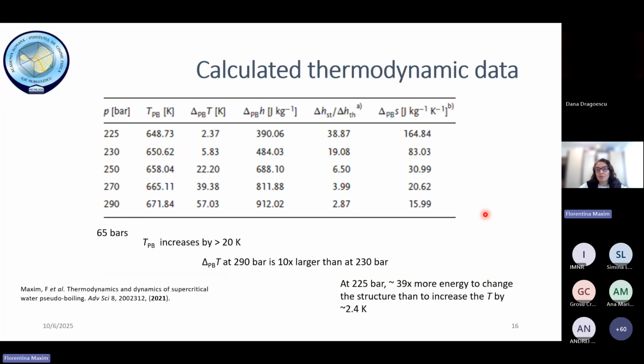Regarding the fundamental knowledge on pseudo-boiling transition in the supercritical water region, we calculated the thermodynamic data by pseudo-boiling theory, and we see that in the 65 bar pressure interval, the temperature of pseudo-boiling is increasing by 20 Kelvin. Also, the transitional temperature interval at higher pressure is larger than at lower pressures. But what is very important, at lower pressure we have a higher supercritical boiling number. That means that the system is consuming more energy at low pressure to overcome the structural changes to heat the fluid.